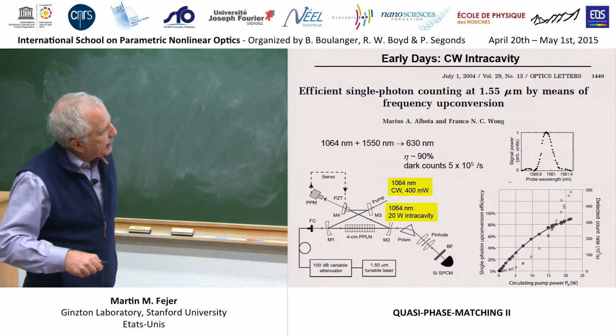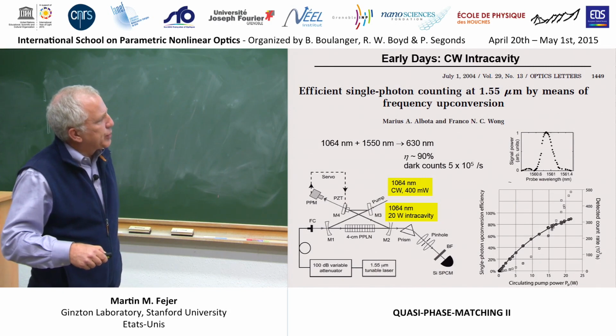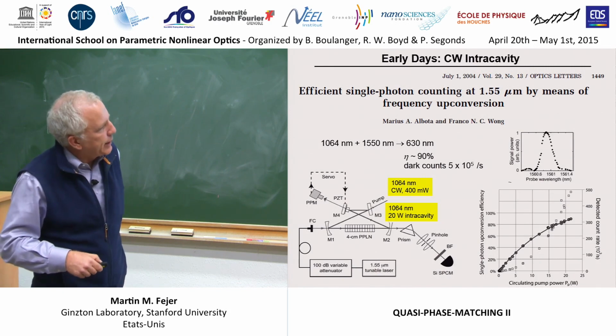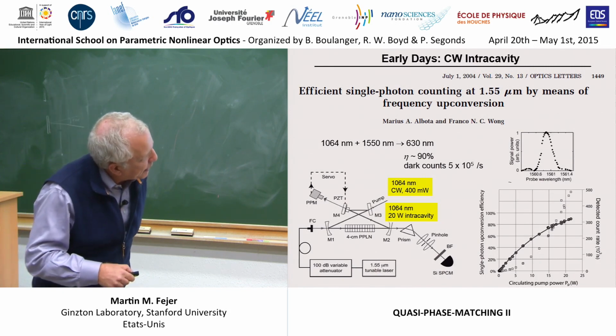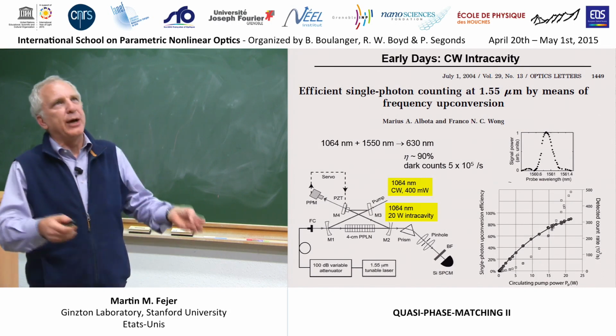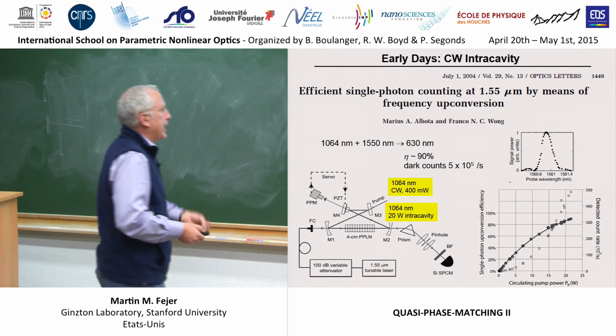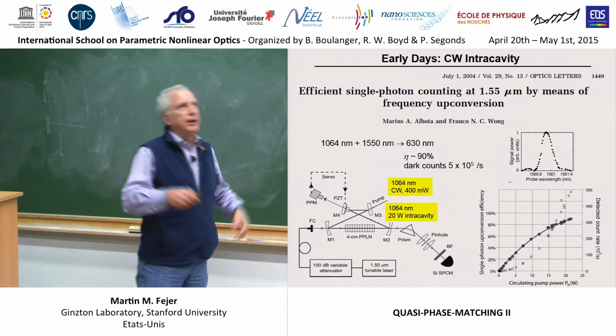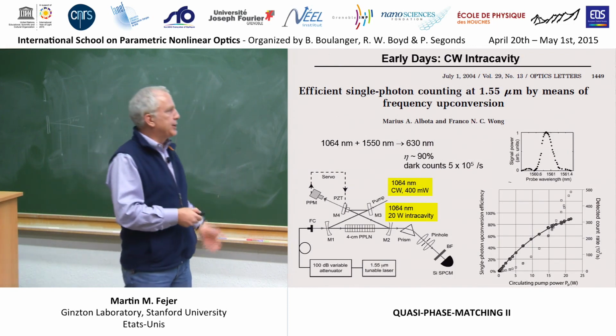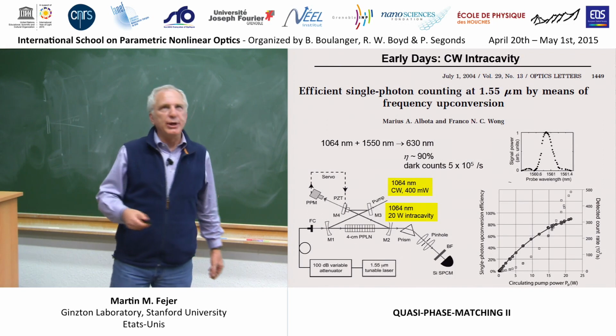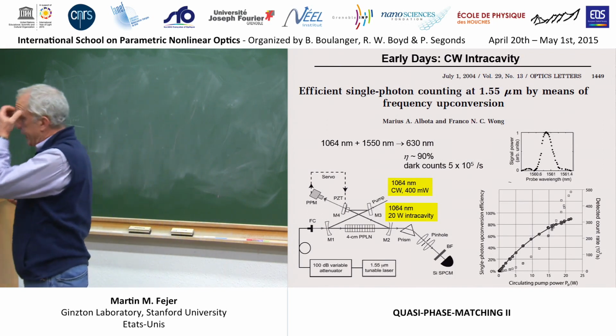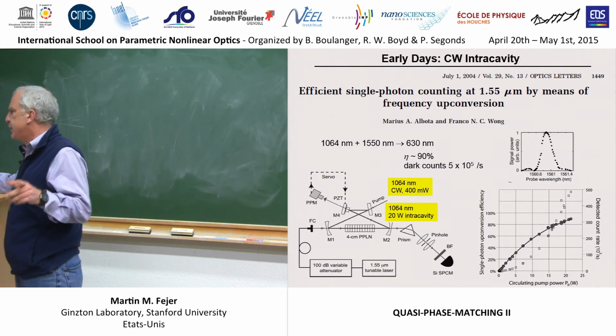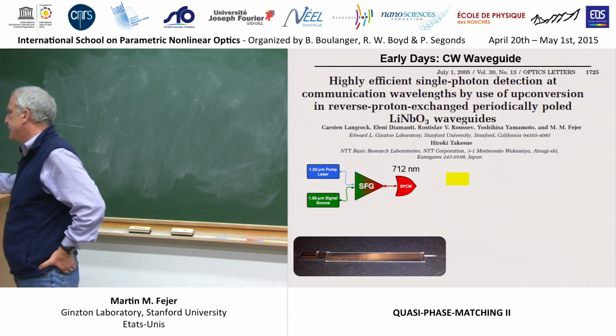So he got to 85 or so percent quantum efficiency, which ain't bad. But if you look at this other line here, he also got to a few 100,000 dark counts a second, which kind of obviates the utility of having a good photon counter if all the photons it's counting are noise photons generated by your up converter. And it wasn't clear what the origin of those dark counts was.